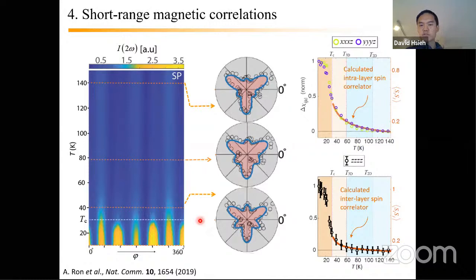And so we think, again, you can look at the paper for details, but there are ways in which we can reason that it's these two elements that are sensitive to the in-plane spin-spin correlator. And similarly, there's another element that we think scales with the out-of-plane spin-spin correlator, which has a different temperature dependence. The 2D correlations build up, and then above some critical correlation length, the C-axis orders.